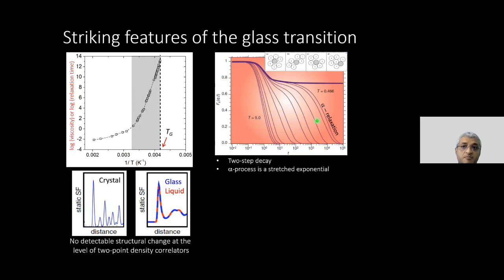But then if I were to look at dynamics, then something remarkable happens. What I'm plotting for you here, and this is a parameter that I'm going to keep coming back to in my talk, is the intermediate scattering function. It's something that you can measure in a dynamic light scattering apparatus. It basically measures particle mobilities. Now, if you're at high temperatures, then you have diffusive dynamics, and this intermediate scattering function is basically an exponential decay. But as you approach the glass state, like I showed you in the first slide, particles are going to get increasingly caged, which means this function doesn't decay but starts showing a plateau. And once you hit the glass, of course, these particles never hop out of their cages, so it's essentially frozen.